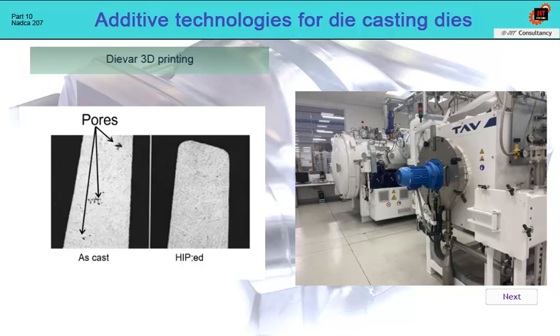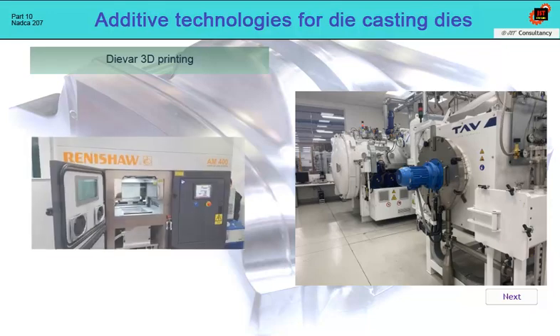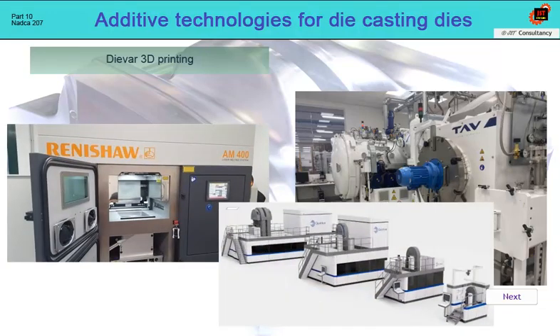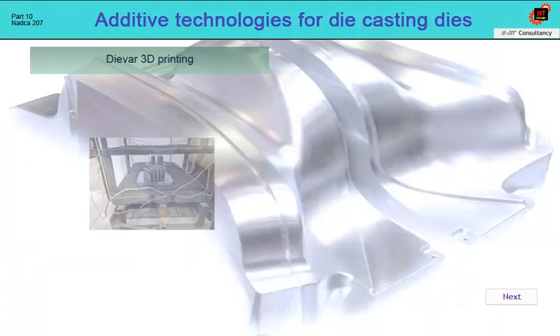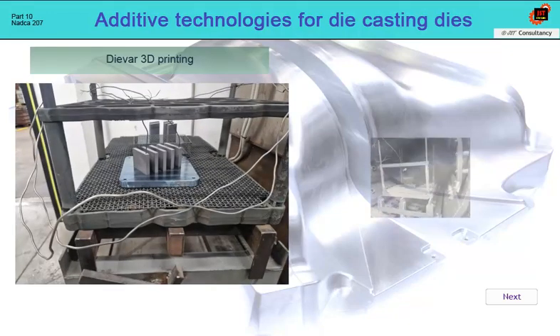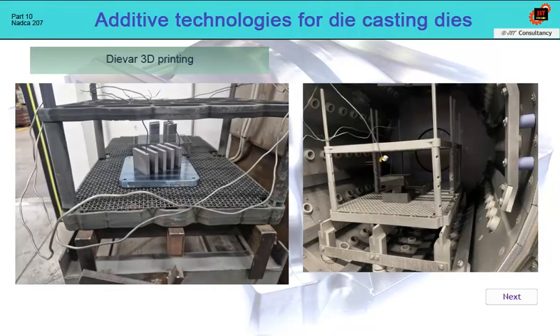And if you're not convinced, even though we have a print density of 99.97%, the material still contains millions of submicron pores. Our process therefore consists of 3D printing, hot isostatic pressing, and subsequent heat treatment in vacuum furnaces. So far, we have tested samples for impact tests according to NADCA 207. To simulate the hardening of real die inserts, the test coupons are placed between two plates, each weighing approximately 13 kilograms. The entire process is controlled by thermocouples TS and TC, as shown in the figure.